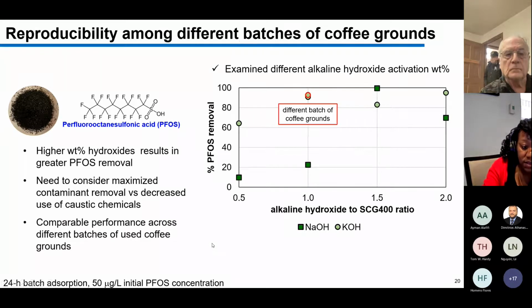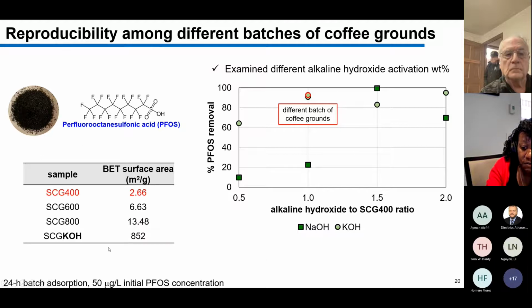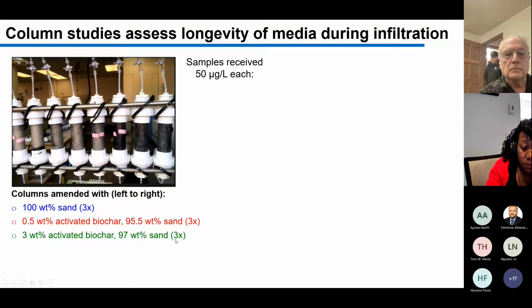So when we did that, we did a second test with a different batch of coffee grounds to see how reproducible is both the initial pyrolysis and this activating step. But we can see that even with a different batch of coffee grounds, we have comparable PFOS removal. So that's good news. And what's even better news is, again, the addition of that potassium hydroxide, we're calling this SCG-KOH for potassium hydroxide, did significantly increase the surface area of our biochar material compared to this very low surface area of the SCG 400 that we started with. So that's great news.